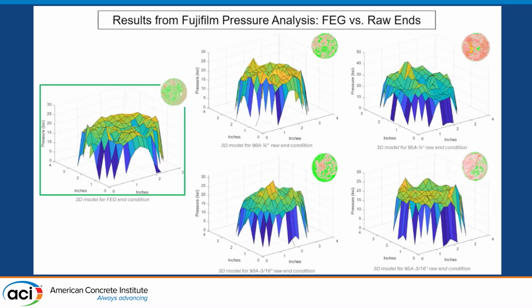And so here are some more models that showed the end distributions. On the left-hand side, you can see the fixed and grinded condition. All of these are within the same batch that was cast. On the top center, you can see 90A and a quarter. On the right-hand side, these are all raw end, so 90A and a quarter. Bottom center, 90A 3/16. On the right corner, you can see 95A and a quarter, and then 95A 3/16.